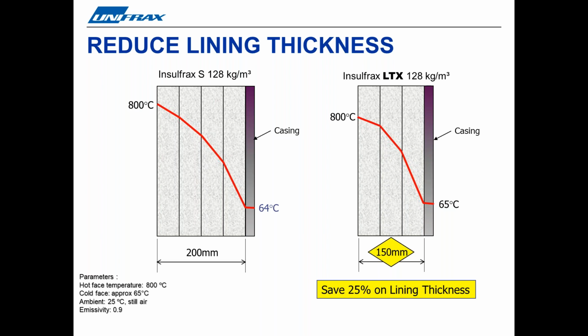However, if users are looking to reduce lining thickness, this example shows how 150 millimeters of Insulfrax LTX blanket can provide the same equivalent thermal performance as 200 millimeters of a standard AES insulation of the same density. So the same cold face temperature can be achieved with a saving of 25% on lining thickness. So this frees up valuable space in furnaces and ovens.